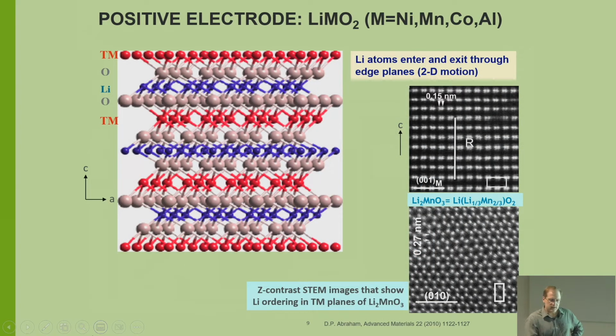All right, this is just a little crystallography, or I should say crystal structure, what's actually in that cathode particle. You have your transition metals, that's these red atoms. Then you have an oxygen layer, then a lithium layer, and then that repeats. When you pull out the lithium, it comes out of that layer. Naturally, if you pull out all your lithium, there's nothing holding that together again, and it exfoliates. So you can generally take about 70% of your lithium out. You cannot take out all your lithium without destroying it; it's like a Jenga. You want everything to stay together so you can put the lithium back in there.